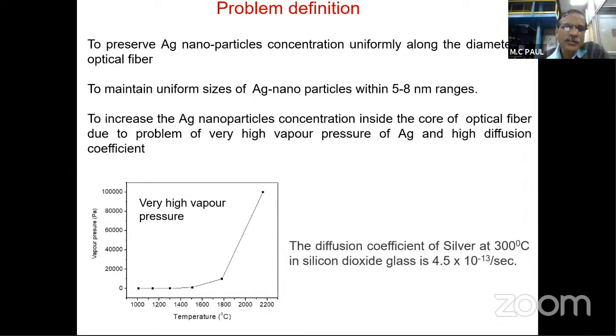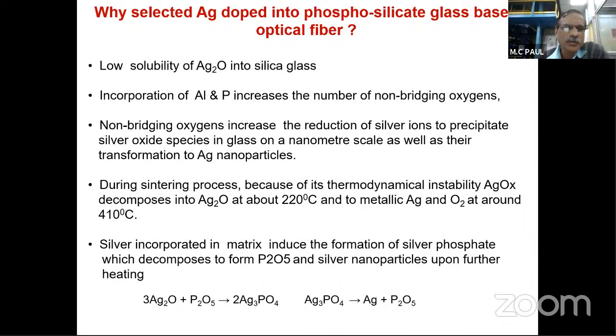Silver oxide has very low solubility in silica glass, and incorporation of aluminum and phosphorus increases the solubility. It also gives rise to non-bridging oxygen, which increases the reduction of silver ions to precipitate silver metal in the silicate glass. During the sintering process, the silver oxide also decomposes and forms metallic silver and oxygen. This is the actual procedure: silver forms silver phosphate, then it decomposes, giving silver and phosphorus pentoxide.